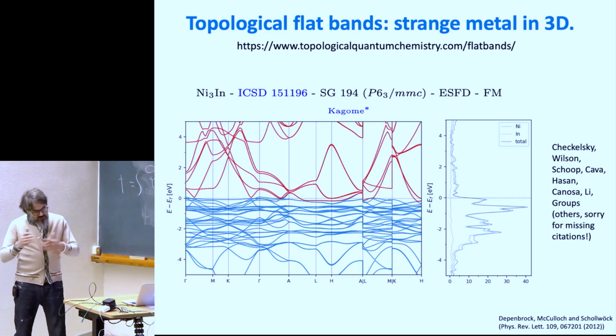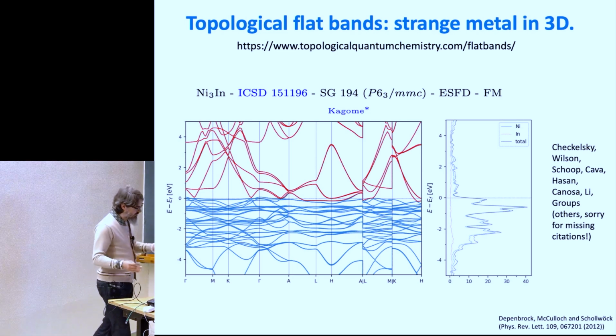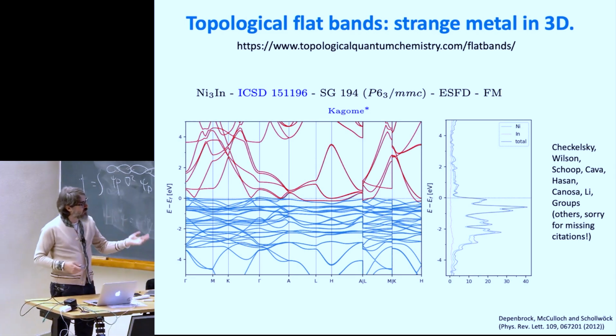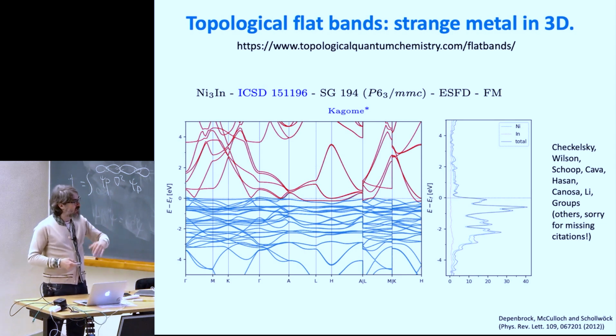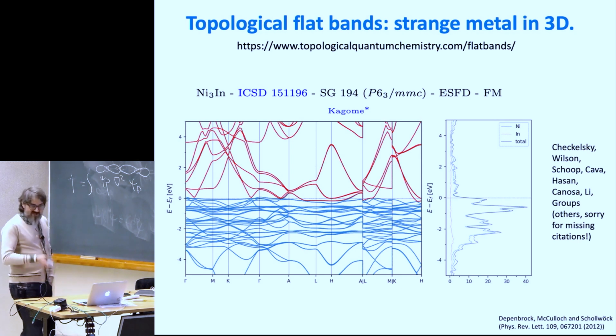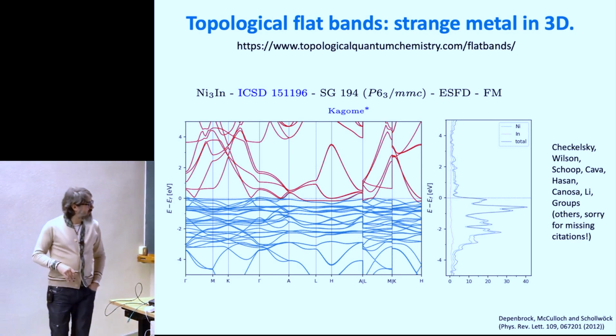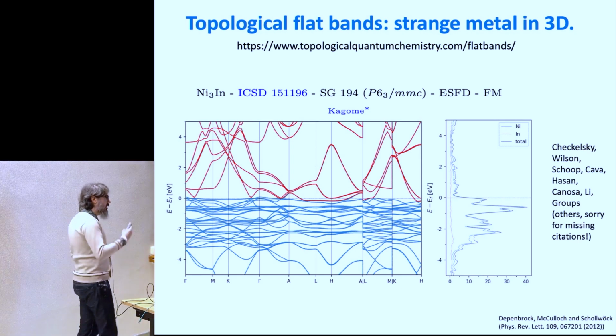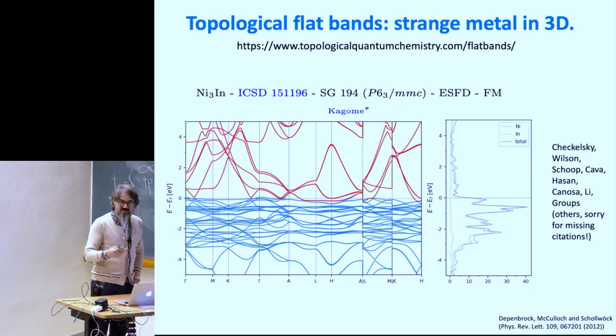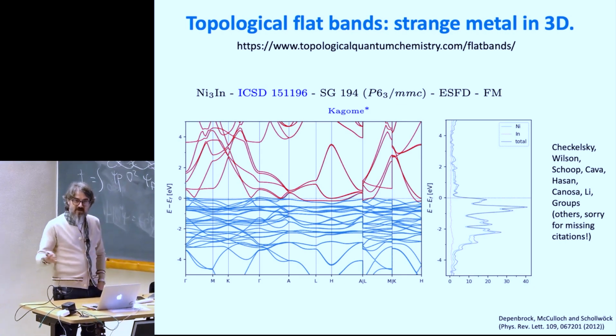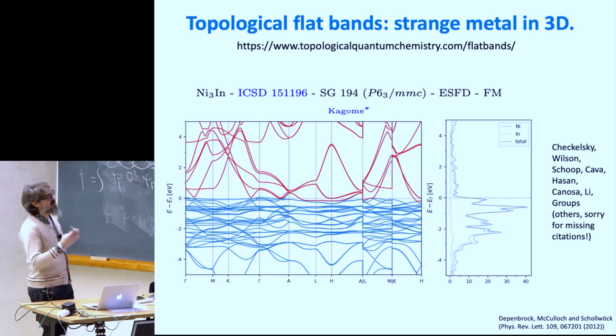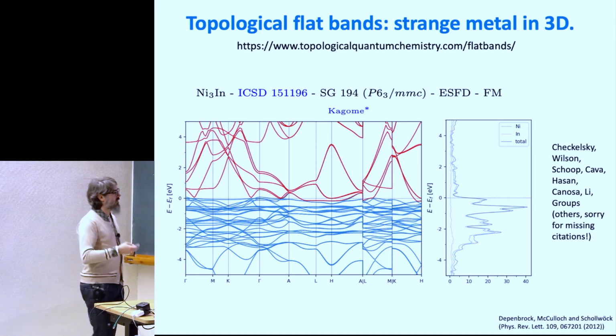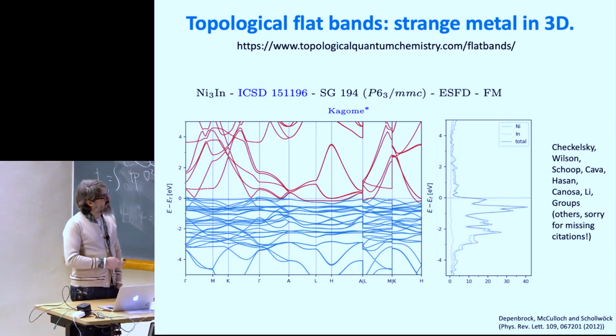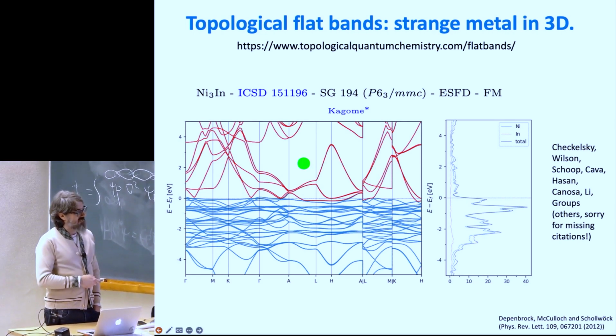There's also a lot of confusion in the literature, a lot of debate about whether flat bands are good or bad for superconductivity. In the end, in 3 dimensions, I think they're bad just because the Coulomb interaction will just ferromagnetize them. But if you could tune the interaction to be purely attractive, flat bands would have much higher superconducting temperature than normal dispersive bands, for reasons that we can go through. They are very easy. But the moral of this slide is to show you that flat bands exist in nature.